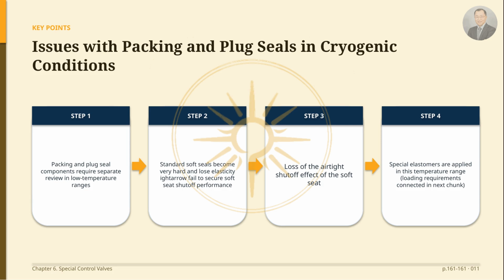I will now discuss the issues that arise with packing and plug seals in cryogenic regions. In these low-temperature ranges, components such as packing and plug seals require special consideration. In the case of plug seals, standard soft seals become very hard and lose flexibility as the temperature drops. Consequently, they fail to provide the shut-off performance expected from a soft seat. In other words, the sealing effect intended for a soft seat is lost.